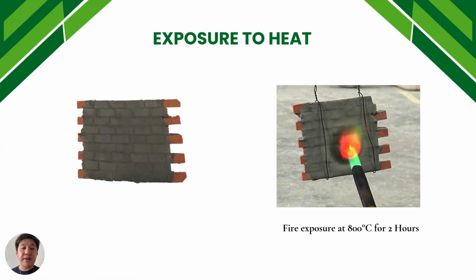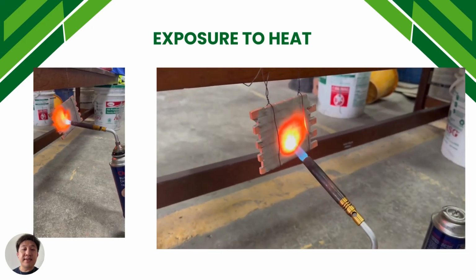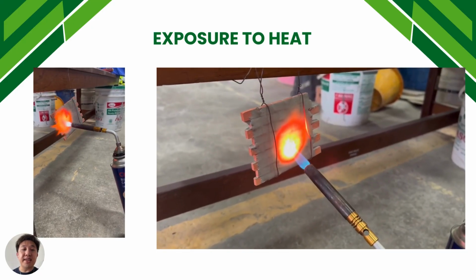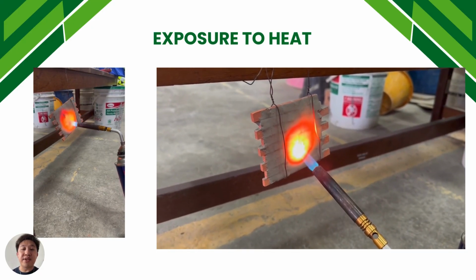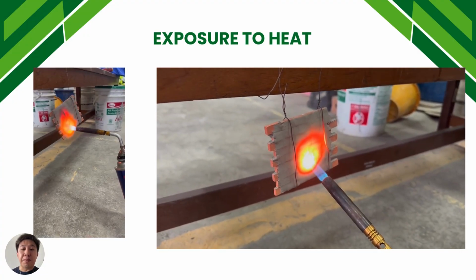And this is the GeoPlaster applied on the surface after exposure to heat. The fire exposure is at 800 degrees Celsius for 2 hours. This is the video on the exposure to heat, as we see that the heat is directly applied to the surface of the GeoPlaster.